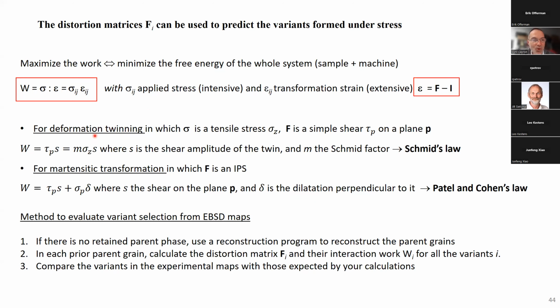So it's very easy to do. Maximizing the interaction work corresponds more or less to maximizing the shear, the Schmidt factor for deformation twinning. Or it also corresponds to calculating the interaction work of this type when you work with martensite, so it corresponds to the Patel and Cohen's law. So it's a very general approach to calculate variant selection. The Schmidt law and Patel and Cohen laws are just specific cases of this interaction work.